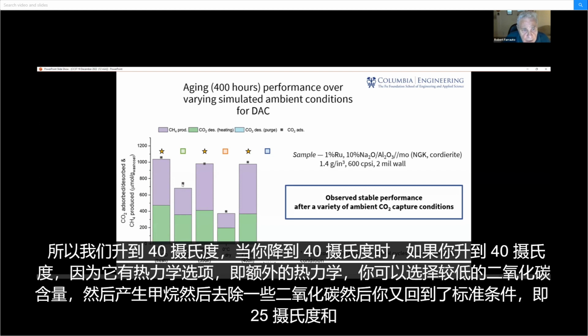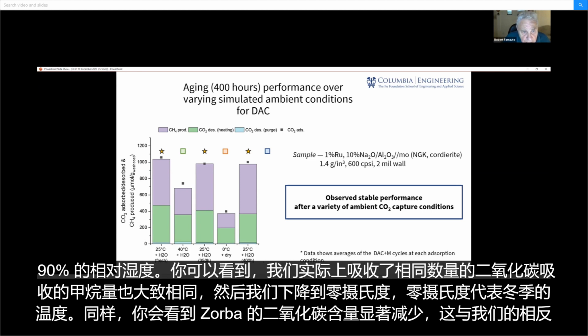So then we go to 40 degrees centigrade, and if you go up to 40 degrees centigrade, because of the thermodynamics of absorption, which is exothermic, you get a lower amount of CO2 absorption, and you get methane produced, and you get some CO2 removed. And then you go back to the standard condition, which is 25 degrees centigrade and 90% relative humidity. And you can see we've got effectively the same amount of CO2 absorbed, roughly the same amount of methane produced as well. And then we go down to 0 degrees centigrade.